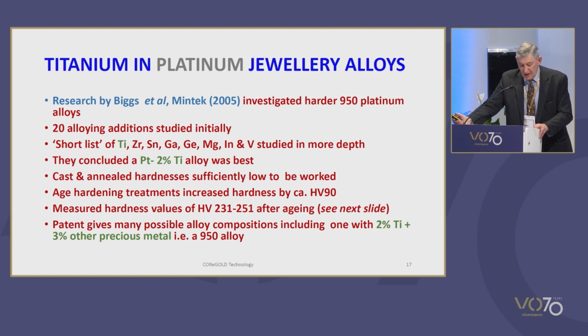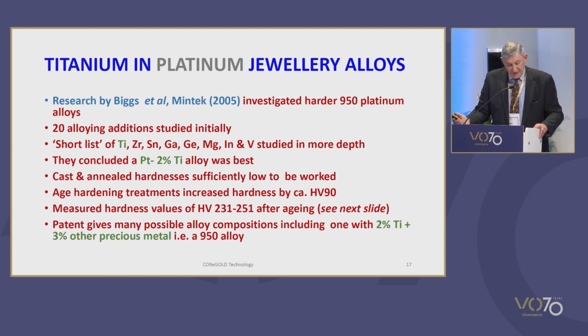Research by Biggs and her colleagues carried out at Mintek in 2005 has examined potential alloying systems for harder alloys aimed at 950 fineness platinum for jewellery application. Over 20 alloying metals were studied in preliminary trials at levels of 2% and 4% addition, and those showing promise were also studied at 3% addition.